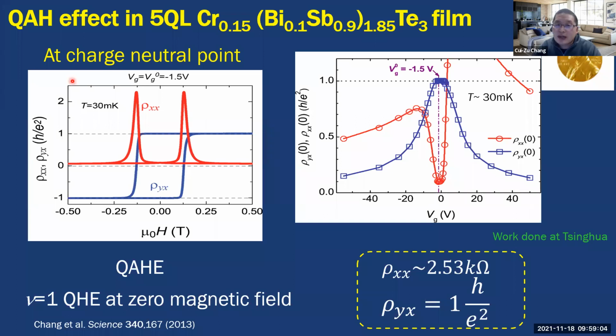So next we optimize the growth condition, change the thickness of the sample, change the bismuth antimony ratio, and change the geometries for the Hall measurement. And with many efforts, in 2013, we were the first to observe the quantum anomalous Hall effect in the 5 quintuple layer chromium-doped bismuth antimony telluride film.